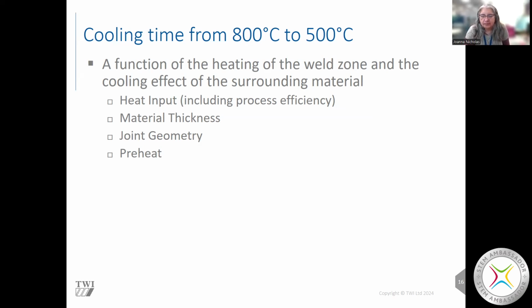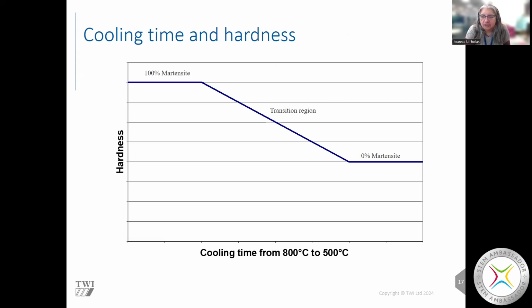Now, in concept, cooling time and hardness are related to each other like this, where at low cooling times, we've got a particular microstructure called 100% martensite, which gives me a hard microstructure, the maximum hardness. And then at large cooling times, we end up with no martensite, so a lower hardness. And in between, there's a transition between the two, where we're moving from that 100% martensite down to 0% martensite. So that concept is what everything else relates to, because we want to have the target hardness, and we might be in the 0% martensite, we might be at 100% martensite, we might be in the transition region.